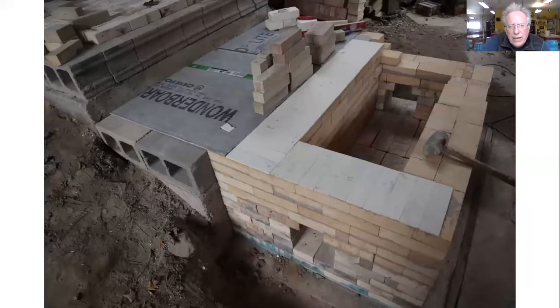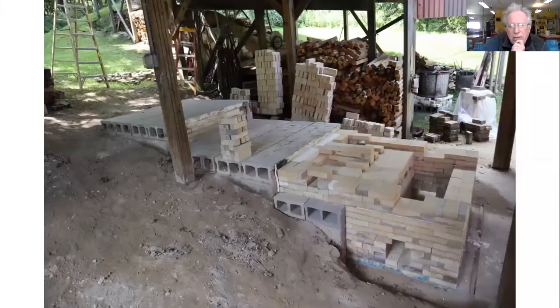So amongst the things that we needed to do in order to achieve that is that we need to bring the different levels up to level elevation. So you see a combination of concrete board, wonder board on the left, and K28s. We use K28s in this kiln, which are a super high temperature fire brick, but are also insulating. So those are shims that helped us level that up. Anytime we needed shims, we went with the K28s. So this is now built up to the first firebox. And that first firebox is inside what will be the inside of the first chamber. Two chambers, three fireboxes, one firebox for each chamber and a main.